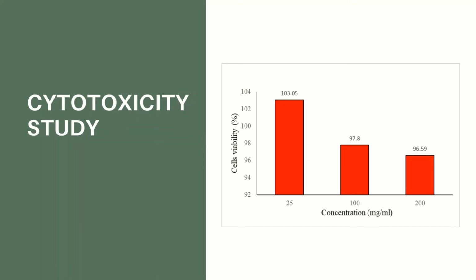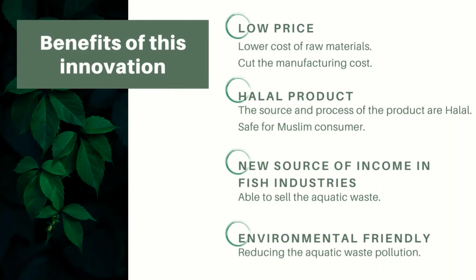In this study, the cells were treated with the leaching solution of collagen hydroxyapatite composite at different concentrations of 25, 100 and 200 mg per milliliter. The overall results demonstrated that the cells exposed to 24 hours of extract showed a high percentage of cell viability, which was above 80% for all composites. These results demonstrated that the collagen hydroxyapatite composite was biocompatible since the cell viability result was above 80% for all tested concentrations. There are plenty of benefits from this innovation.